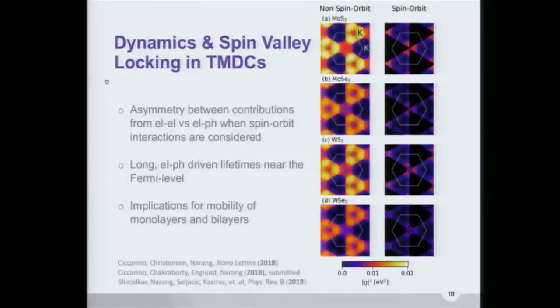Not quite the case. So on this chart here, I'm showing you the effect of spin-orbit coupling. Without self-consistently including spin-orbit coupling, you would grossly overestimate the electron-phonon coupling. As a consequence, you would say the electron-phonon time is much shorter than what it actually is. You'd also, both qualitatively and quantitatively, predict the mobilities in these materials incorrectly.